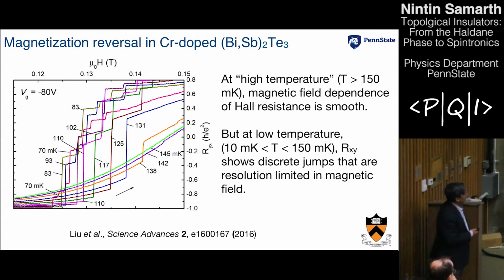When he sweeps the magnetic field extremely slowly, he finds that once you are at temperatures above the base temperature at which we were seeing the precise quantization, the switching is no longer some kind of smooth process, but occurs in very, very sharp, discrete steps. And these discrete steps are limited in resolution by the magnetic field sweep that you're doing. So this is very, very puzzling.